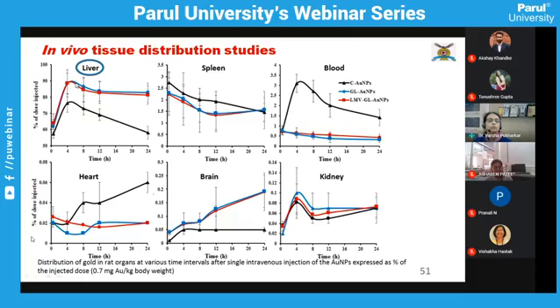So we could see that there is a considerable amount of the drug present in the liver when given as the glycyrrhizin reduced gold nanoparticles. Whereas in the case of citrate reduced, the amount in the liver was pretty low, but there was a high concentration of citrate reduced gold nanoparticle found in the blood itself. So they were not much taken up by the target site, that is the liver.